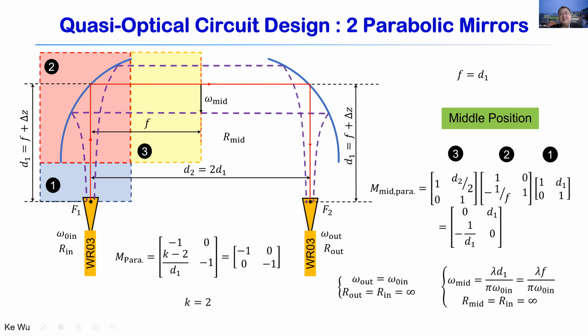For the parabolic mirrors, this gives us a much better solution, because in this case you have planar beam propagation between the mirrors here. So D is naturally equal to 0 here, or delta equal to 0. In this case, you can create very good, arbitrary, unlimited thickness measurements. So this type of parabolic system is adopted in our laboratory. We like these measurements better than that.